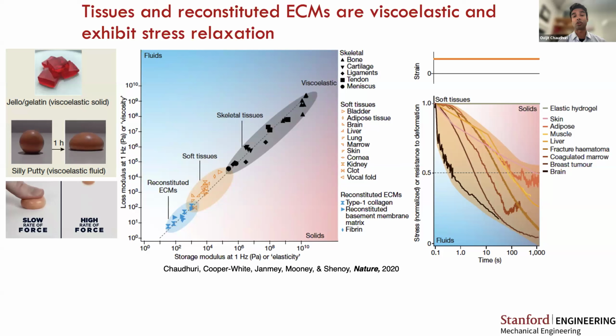Now, there's various ways to describe viscoelasticity, and we typically describe viscoelasticity in terms of stress relaxation. And the reason is because it gives us somewhat of an intuitive idea of how cells might respond to viscoelasticity. So if we imagine a cell first binding to a substrate and pushing or pulling on that substrate, initially, there's some resistance as defined by the initial elastic modulus or stiffness. But over time, that resistance to deformation relaxes as related to these stress relaxation properties in the material.